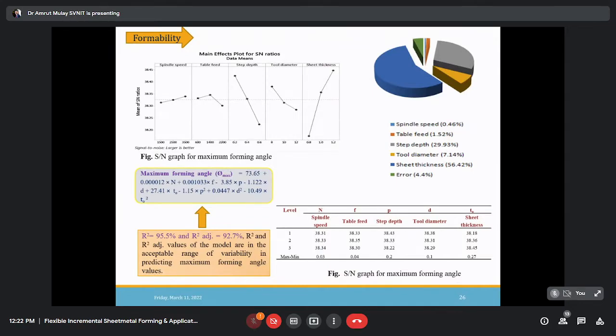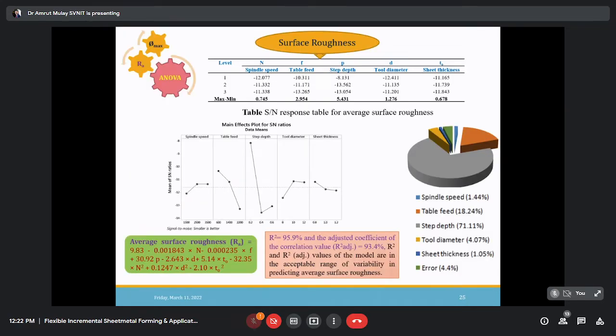You can see spindle speed in the case of formability. It is very small effect. You can see the sheet thickness has significant effect, step depth has significant effect, but spindle speed has very slight effect. And even in case of here, you can see spindle speed has very slight effect. Therefore, we removed this parameter in the further course of study.